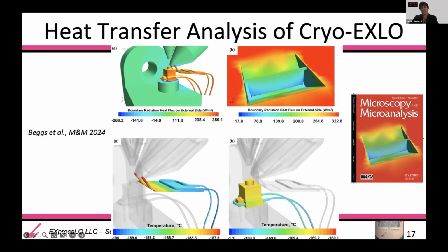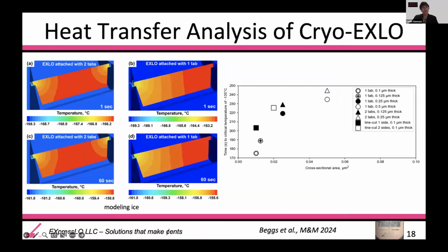This is our thin specimen, and what this shows, as we go to the next slide, is that if we alter the size of these remaining tabs of the specimen, again, the red to the blue is a little deceiving because this is only a couple of degrees C. But you see that the warmest part of the specimen is going to be at the part that has the thinnest amount of material. And this shows time to critical temperature as a result of cross-sectional area.